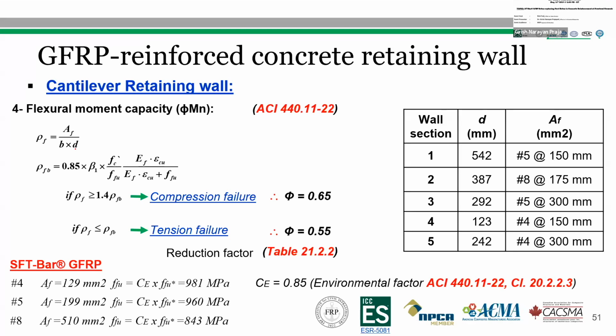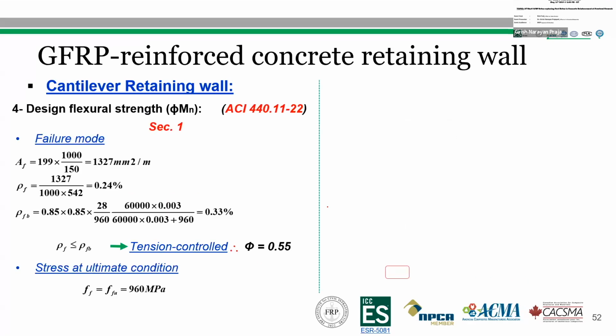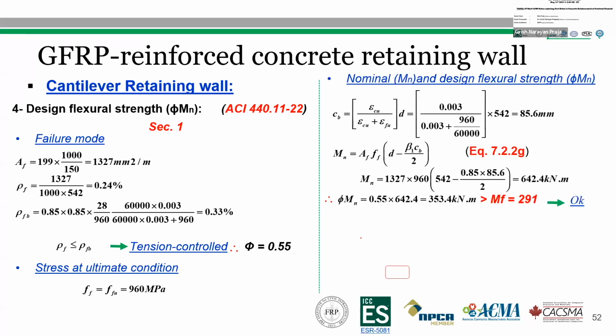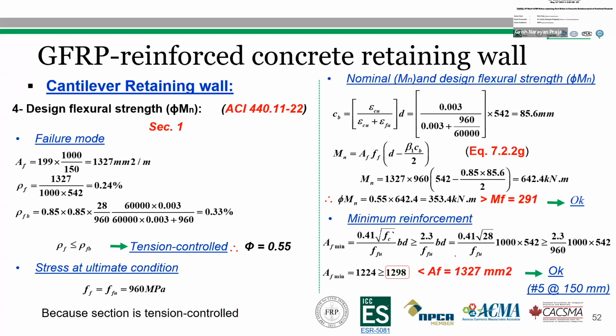The design tensile strength of the different sizes of SFT GFRP bar can be found by multiplying by 0.85, which is the environmental factor according to ACI 440.11. The design flexural strength of section 1 of the stem was calculated by assuming 1 meter width, and it was found that the reinforcement ratio was lower than the balanced reinforcement ratio. So the section is designed as a tension control section, and the provided reinforcement was checked with the minimum reinforcement because it was a tension control section.